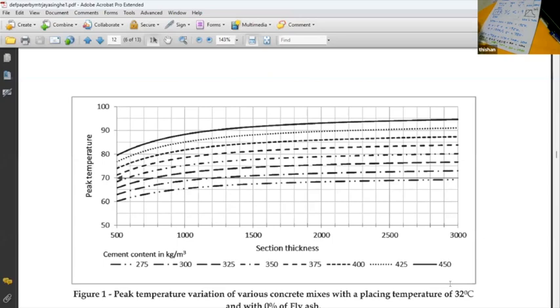So by looking at this chart, you can decide what you are going to do. But my advice is, if you are having a large pour, it is because you have not optimized the design. If you have not optimized the design, what are you going to do? Don't use high strength concrete. High strength concrete needs a high amount of cement. High amount of cement means we are asking for trouble. So if you have not optimized the structure, you have a large pile cap, use 30 megapascal.